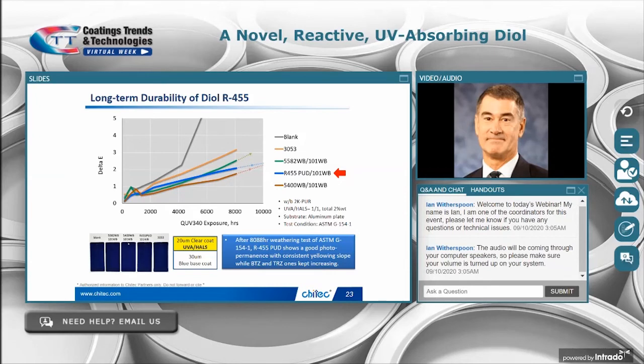And here are the results. And as you can see, the blank is terrible. And then the standard line is the green line with a free UVA, which is doing okay. And then the R455 is doing better. And then the triazine is also doing quite well. And keep in mind that in this experiment, we are not doing any extractions or other migration enhancing testing. So in the real world, if anything, we expect the R455 to perform even better than this particular graph shows.